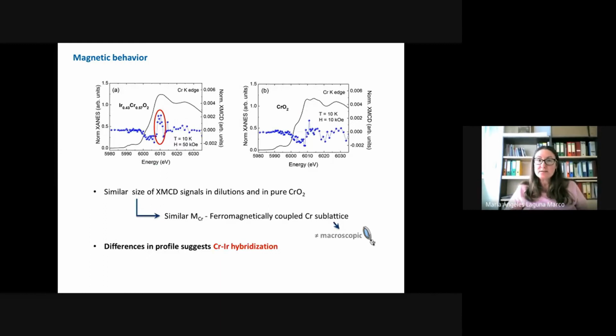As for the chromium sublattice, the similar size of the XMCD signal recorded at the chromium K edge on both doped and undoped compounds indicates a similar net magnetic moment in the chromium sublattice for both systems. However, looking more in detail, we can see that the doped sample presents an extra feature that is not observed in the parent compound. This can be associated to an iridium contribution, in turn associated to a chromium-iridium hybridization.